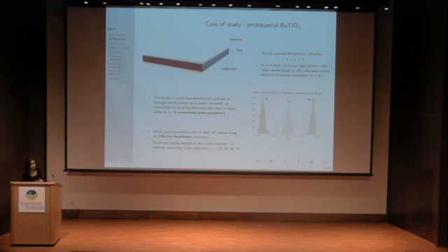And this morphology allows the system to be regarded as quasi 2-dimensional. And the order parameter, so the local dipole moments, the polarization, has two essential components, the Ux and Uy. So it is confined to lie within the film plane and is free to rotate within it. And this is, for instance, shown in the distribution of local dipole components, where we see that the Z component is a Gaussian centered on 0.